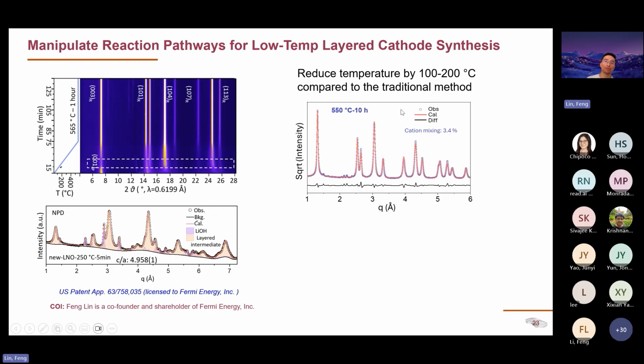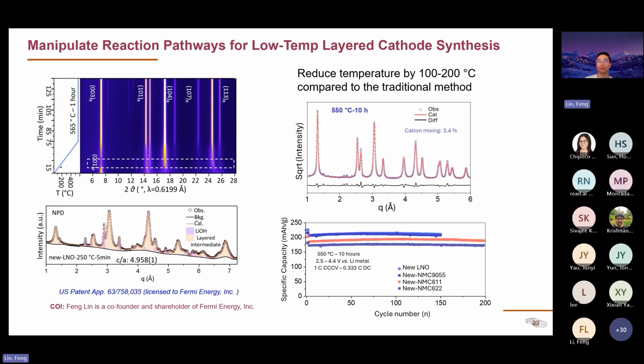I didn't mention the crystal structure too much. Cation mixing means that lithium and nickel are mixing their sites. Ideally, you want to have lithium on the lithium site, nickel on the nickel site. You can potentially allow a few percent of cation mixing, which will be okay. And some people found that a few percent actually is beneficial for the performance, but you cannot allow too much nickel and lithium cation mixing. So our cation mixing is very low, and they also perform extremely well in long-term cycling.